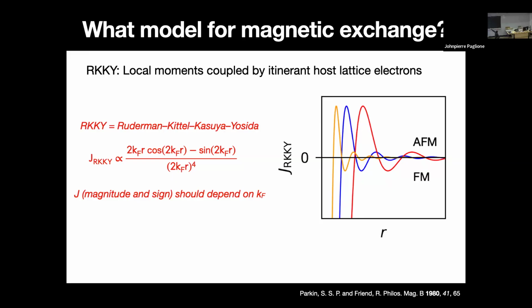All right. So the assumption is that the model for magnetic exchange is RKKY, which is sort of a model that says, all right, I have local magnetic moments, and these are coupled together. They talk to each other through some itinerant electrons in some conduction band. And so what that means then is that the magnitude of the magnetic exchange J is going to depend on the Fermi wave vector, basically in effect the carrier density, if you will, or more accurately, the Fermi wave vector, and the distance between the ions, so that you have this oscillation between positive and negative J's that gives rise to whether ferromagnetic or antiferromagnetic interactions.